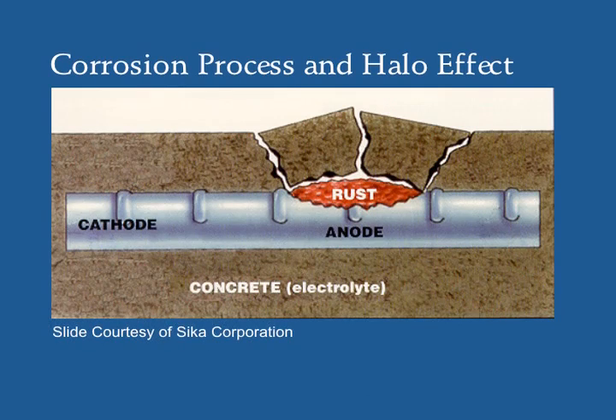This schematic, courtesy of the Sika Corporation, gives us a picture of the 4 components of the corrosion circuit, namely a cathode and anode and electrolytic path, which is provided by the pore water, and a metallic path, which is the steel itself. As chloride concentrations increase around the rebar compared to other locations, that location becomes the anode, and that's where the actual corrosion occurs. Because rust itself is 500 to 700% larger in volume than the parent material, it produces a bursting stress within the concrete.